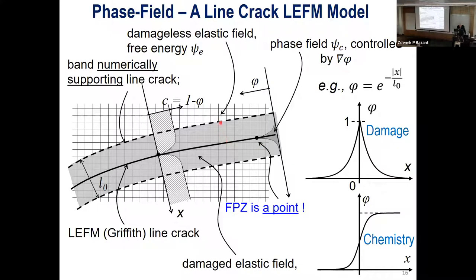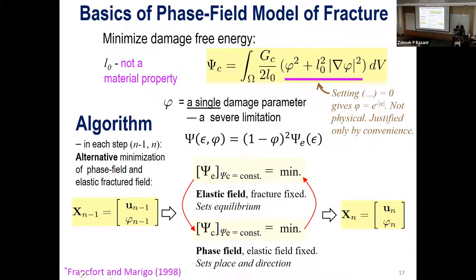So that's achieved by having a band of width of about 4 to 6 elements, and the damage comes out like this, an exponential function. And this is then applied to the elastic field, which variationally anchors the band to the right place of propagation. It works beautifully. That's an outstanding idea. Outstanding idea of Francfort and Marigo about 20 years ago. So the fitting of the crack band onto the finite element is done variationally. We minimize the damage free energy.